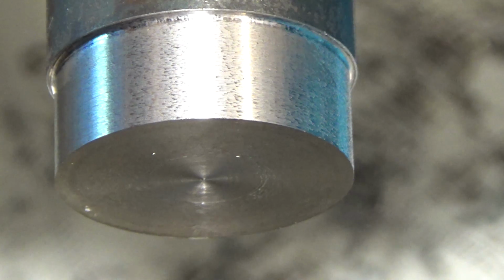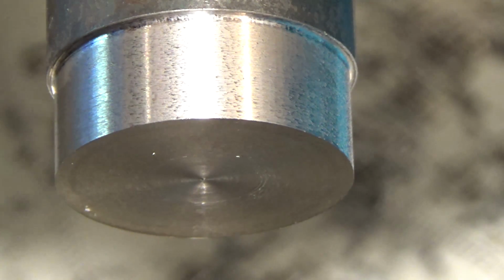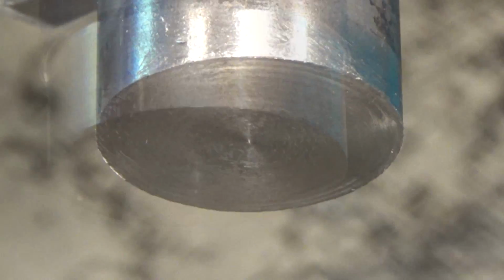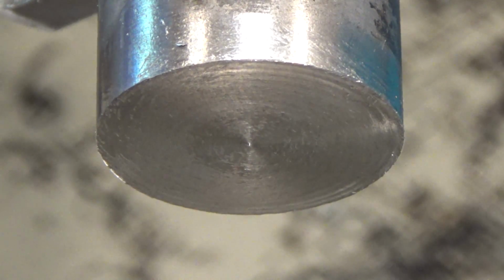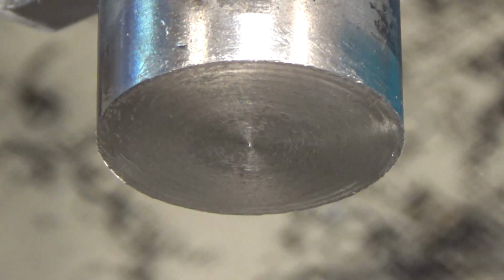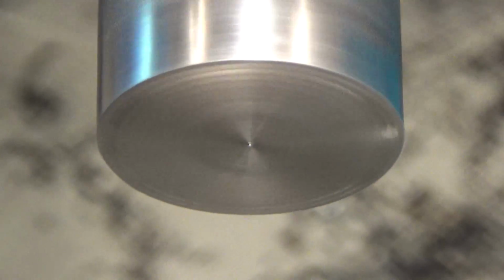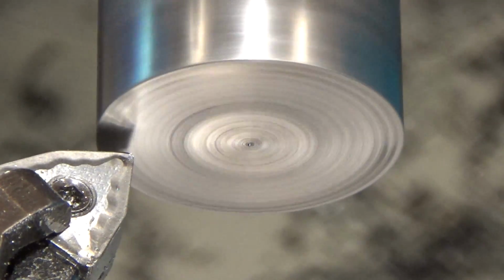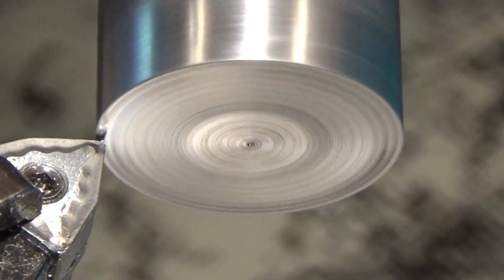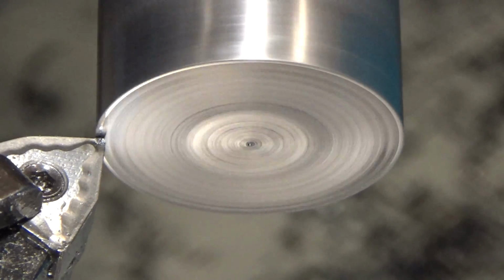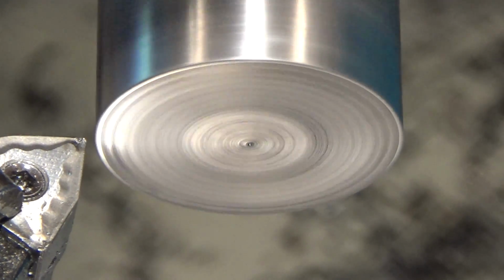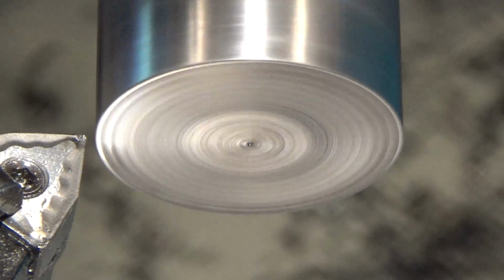All right, let's move on to the heat-treated but not tempered, the hardest stock of them all, probably between Rockwell C 54 and 59 hardness. So finally we are on the heat treated but not tempered. Like I said earlier on several occasions, Rockwell C 54 to 59. We're going to start with a facing cut at slow speed. I was squaring this up, and I don't think I can do 25 thousandths depth of cut very easily. So I'm going to zero that, and I'm going to do 10 thousandths, which I know isn't fair, but this material's a lot harder.